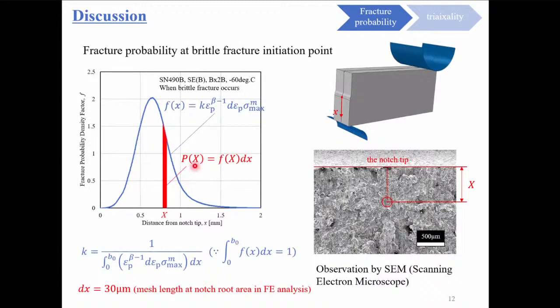the brittle fracture initiation point is limited to the longitudinal center of the specimen and the mid-thickness. The probability density function is treated as a function of the distance from the notch tip. By observing the actual failure location of each specimen using the SEM, the probability that the actual location is a failure location can be determined. This allows us to determine which Weibull stress model is the most likely in terms of failure fracture probability.